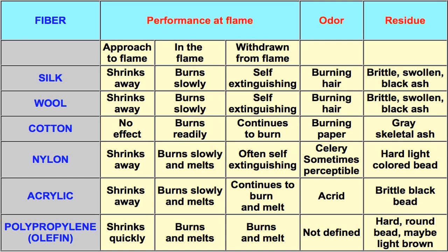Whereas in case of nylon, often self-extinguishing, not always, often self-extinguishing. In case of acrylic, it continues to burn and melt. So in case of silk and wool, it will extinguish. In case of acrylic, it will continue to burn and melt. And the polypropylene also, it will burn and melt even if we take it away from the flame.